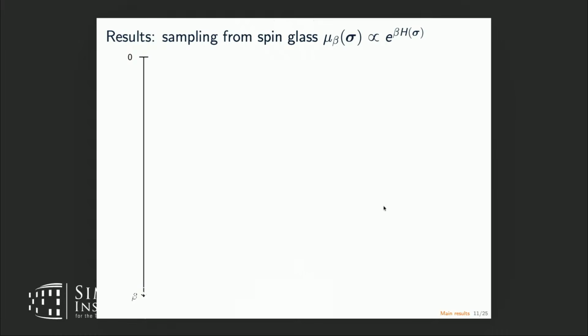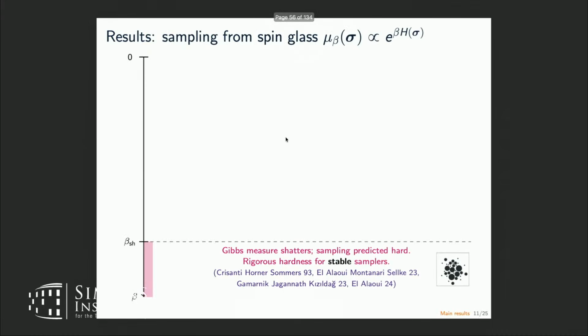We're now ready to state our main results for sampling from the spin glass. I'll plot the inverse temperature parameter beta on the vertical axis, and I'll first state what was previously known and where our results fit in. It's expected that for any beta bigger than the shattering threshold, the Gibbs measure shatters and all polynomial time algorithms will fail to sample. Rigorously, it's known that suitably stable algorithms will fail to sample in this region. And it's also predicted that anywhere up to shattering, the Langevin dynamics from random initialization will succeed.